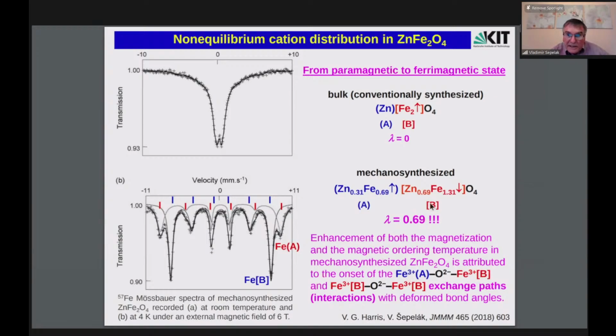And so we have a very nice picture of both cations, zinc and iron, in the structure of this material. From the intensity we can also calculate the degree of inversion, and it is almost identical with the information obtained from XPS and Mössbauer spectroscopy. The main enhancement of both the magnetization and magnetic ordering temperature in this material can be attributed to the onset of exchange paths iron on tetra, oxygen, iron on octa sites, and also exchange paths iron on B sites, oxygen, iron on B sites with deformed bond angles. That means now we have elucidated the origin of this enhancement.